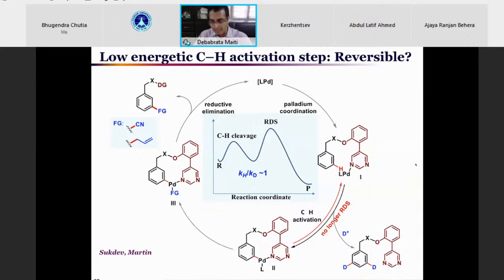Well, one of the things that was also happening with this ligand is that now we have an opportunity to make the carbon-hydrogen bond activation step reversible as well as not the rate limiting step. As you can see over here, this key step, the carbon-hydrogen bond activation step, is no longer rate limiting and it becomes reversible. If that's the case, we can introduce deuterium by utilizing a D plus source, like deuterated acetic acid, let's say. We can introduce the deuterium selectively at the meta position of the organic substrate.